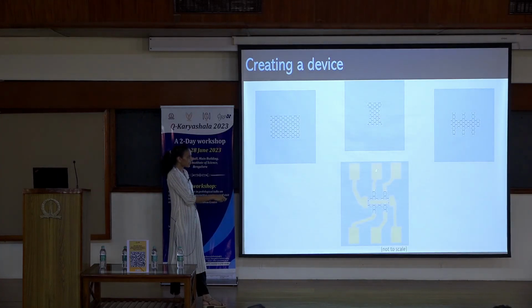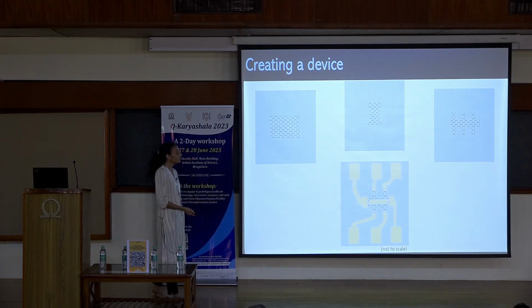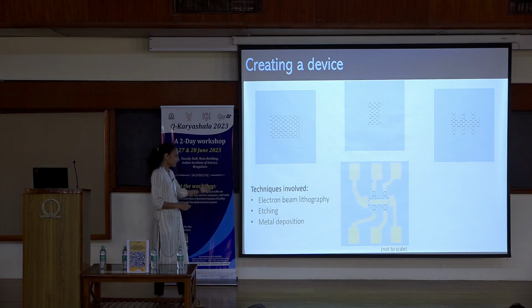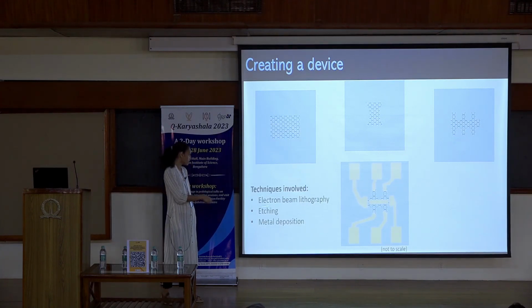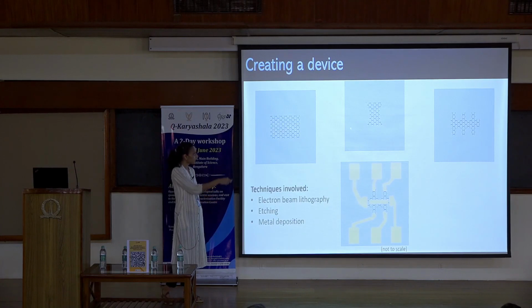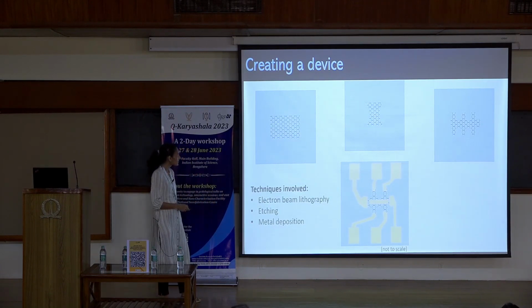And then you put these electrical contacts, these are gold contacts. This is again not to scale, using some of the tools that we have in the SENS facility. These are ohmic contacts to this 2D material. Now the techniques involved, I'll not go into the depth of it, but you can Google about it if you're interested. Electron beam lithography and etching are used to pattern this into the shape that you want, and then you deposit metals on top of it. These are the 3 techniques that are important to create these devices.